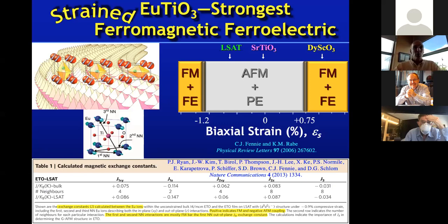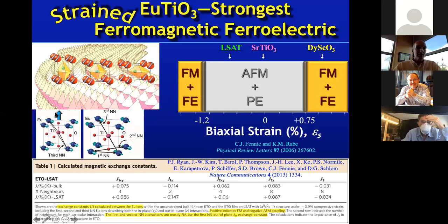Now let's imagine what happens when you put europium titanate in biaxial compression. So biaxial compression corresponds to this cartoon that I have over here on the left. And in the computer, what that looks like is that the titanium, or at least in PowerPoint, you can see that the cage is elongated in the out-of-plane direction. So the titanium wants to go off center so that it can bond to these oxygens that are on this side of the octahedron. When the titanium goes off center, that affects the super exchange along the body diagonal. So what was effective antiferromagnetic super exchange through the titanium is going to be weakened as the titanium goes off center.